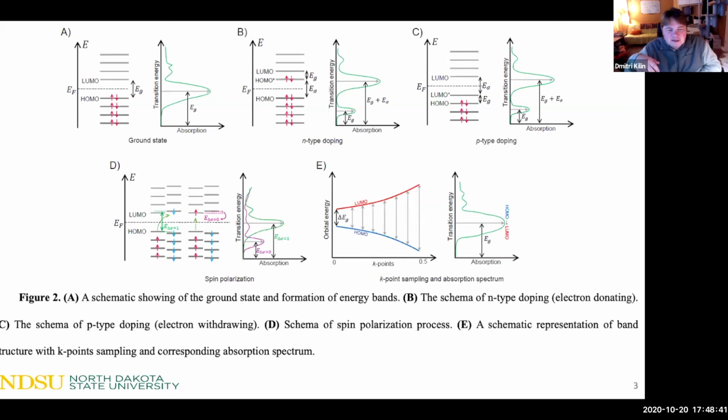In a substantial number of experimental systems, one first excites the system in a singlet without spin flip. So the red electron goes up from HOMO to LUMO. And then through intersystem crossing, it converts to the triplet. So it goes to the spin flip configuration. In this calculation, you are not computing the mechanics of such a transition.